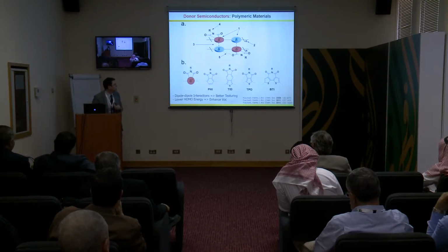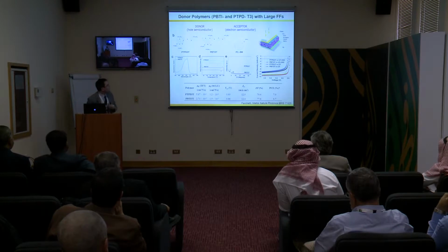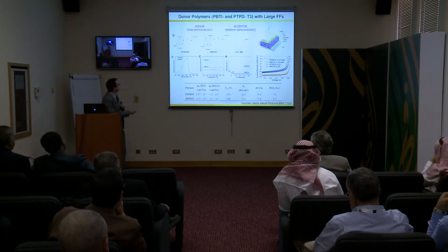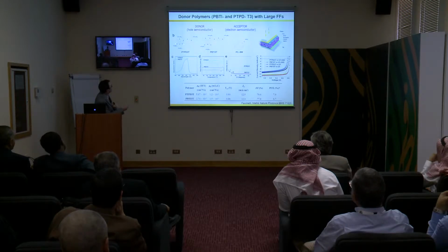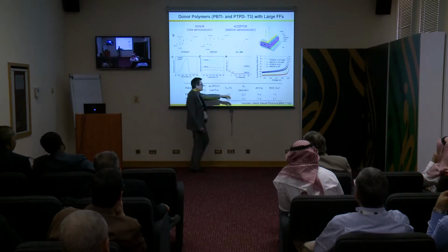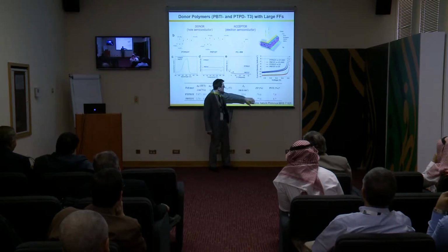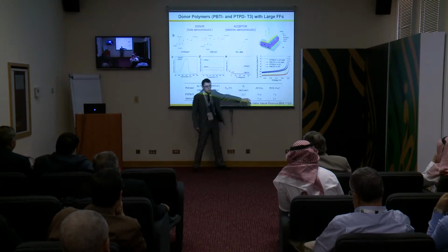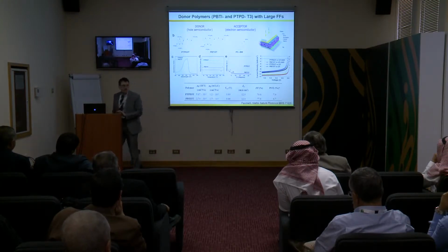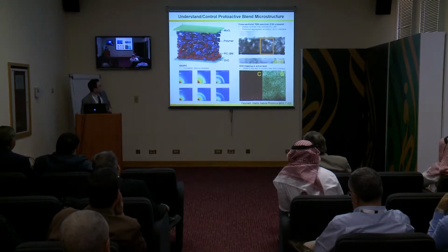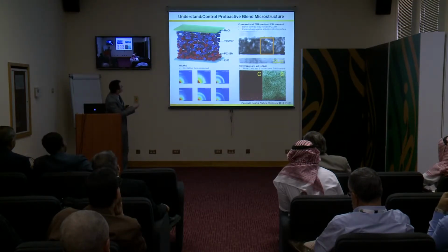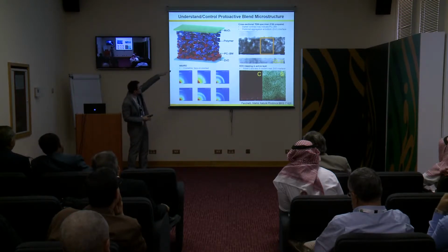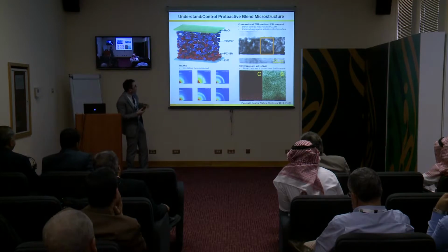So this type of unit was quite suitable, and this is a very old work, as of 2013. But we have shown that when we use this imide functionality copolymerized with a 3T type of unit, we could achieve a decent efficiency for the time, between 7 and 8%. But the fill factors were very, very large, very unusual for the time. We tried to rationalize the high fill factor because of the uniqueness in the morphology, where you have your acceptor with zinc at the bottom, very nice face-on orientation of the polymer stack, and the right phase separation.